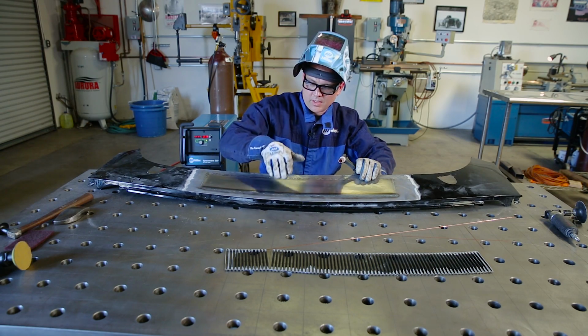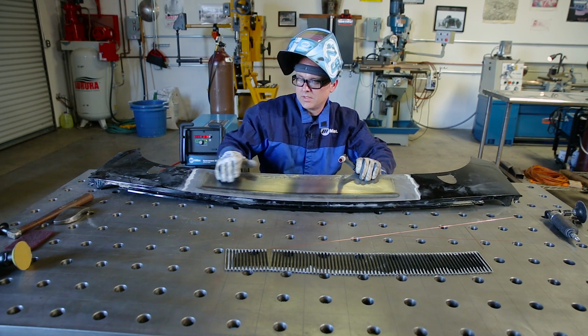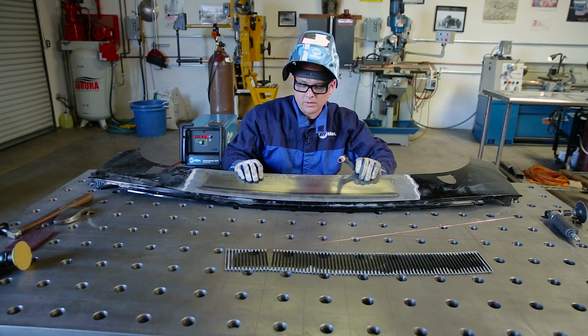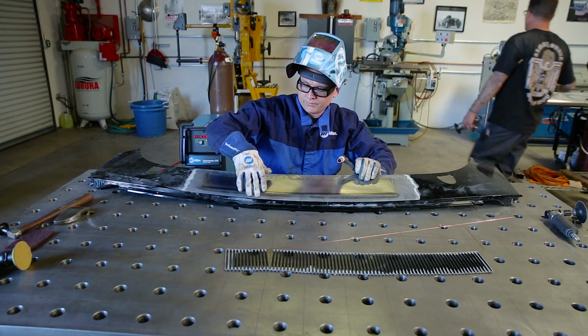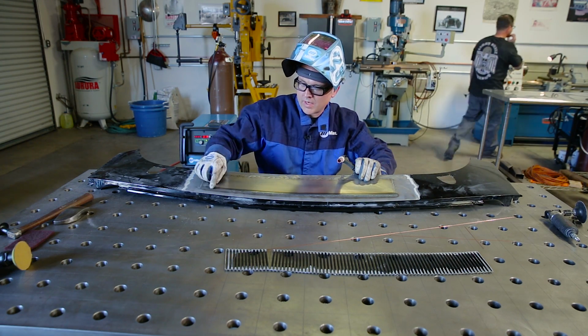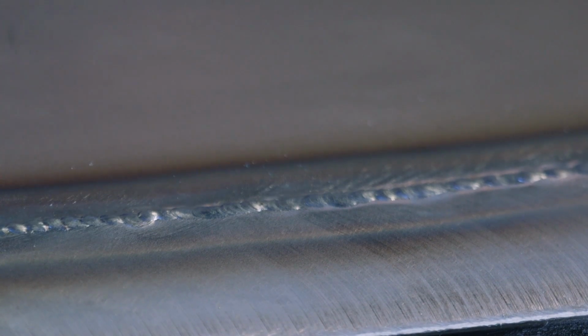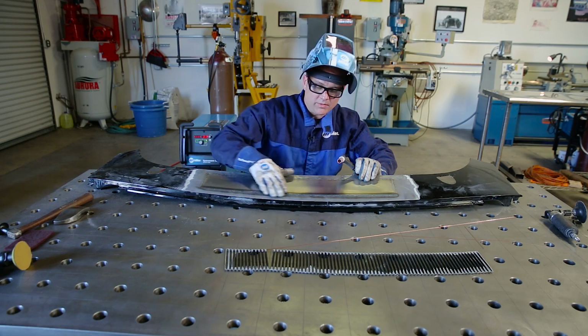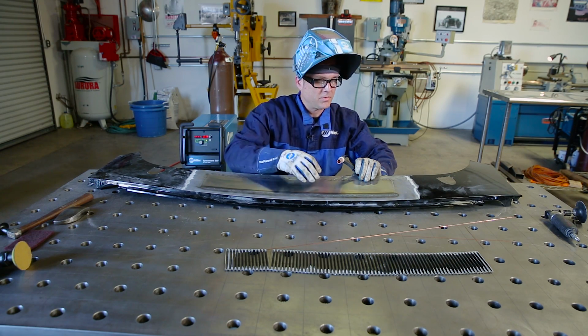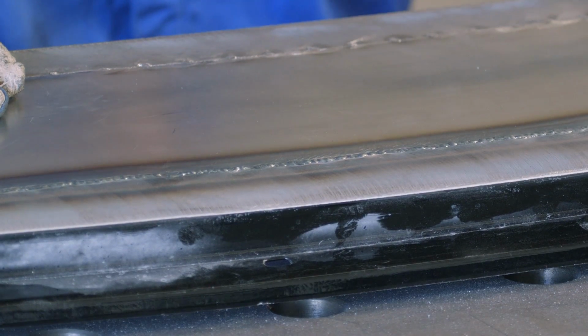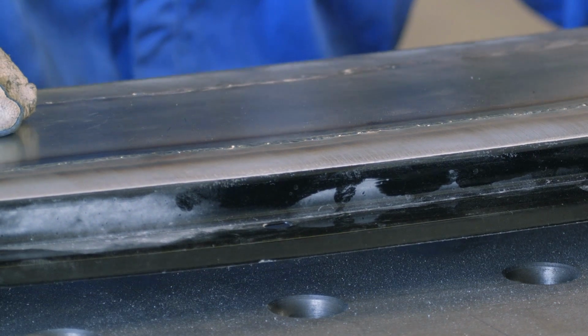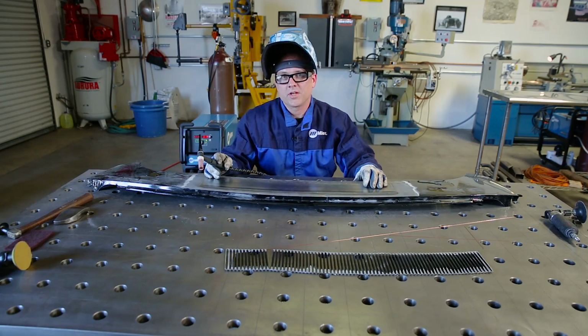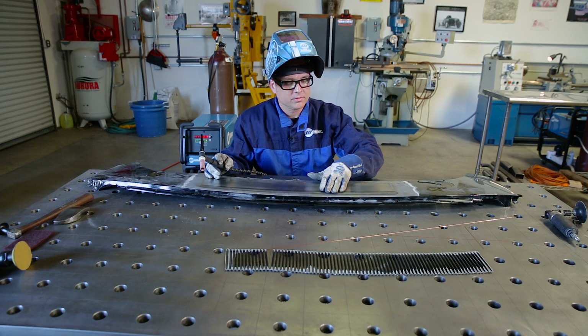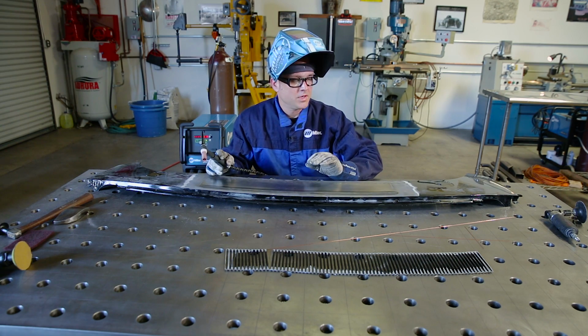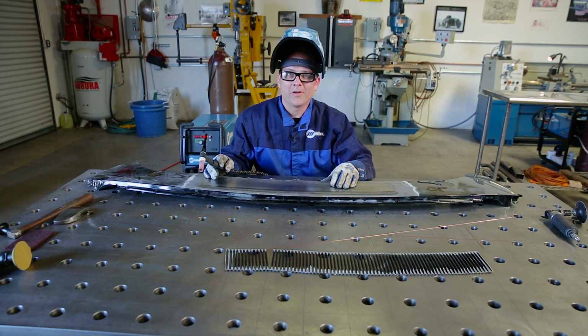I actually have a slight crown this way, which is easy to take out by planishing it later. And by it crowning this way, I can easily sand my weld and take that off and then planish it back down flat. But it's a nice even heat across, so it has shrunk the same all the way across, so it doesn't really warp up your piece as bad. So it came out very well. Now I'll finish out the rest of the welds and sand, planish, and it'll be ready to put back on the car.